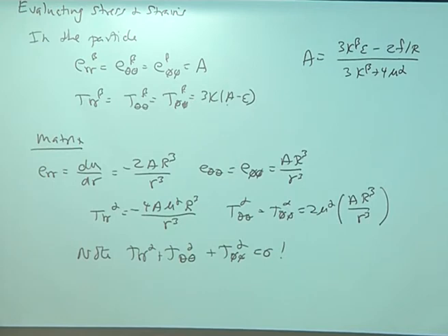It'll be stress-free, but only for a particular size. So if you go from some other size to that size, then everything will stop. The stress will be 0, because the surface stress, one is pushing out and the other is pushing in, and they balance at exactly the right place.